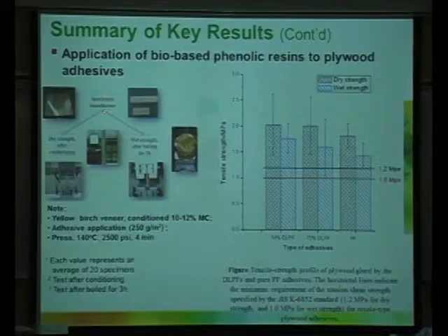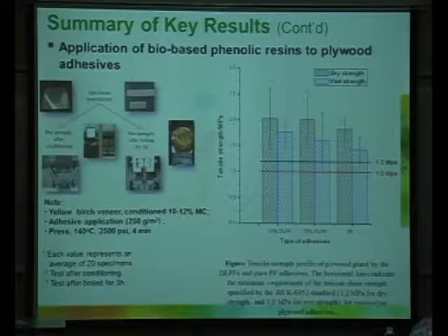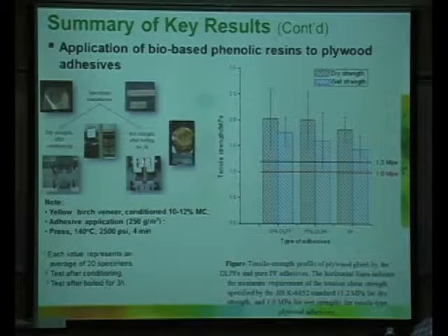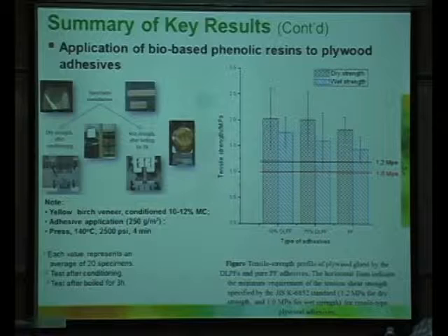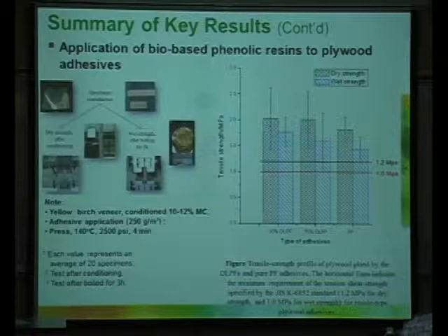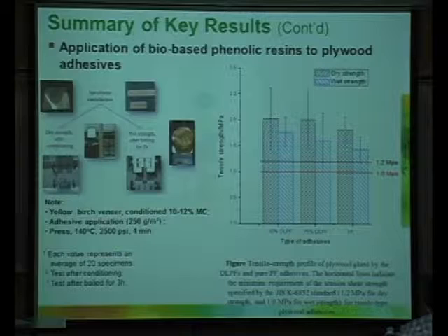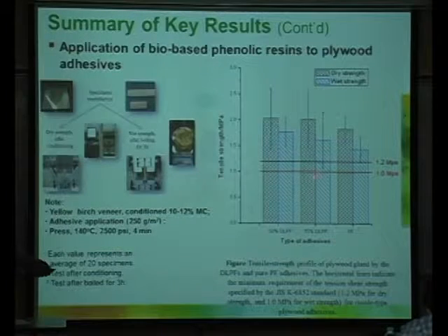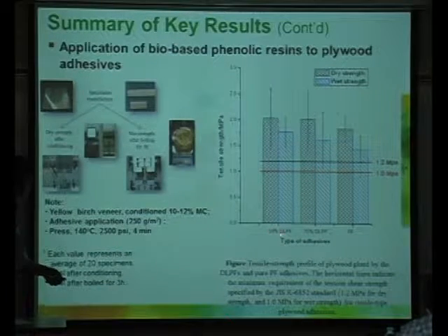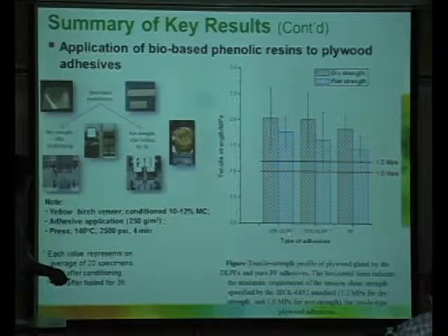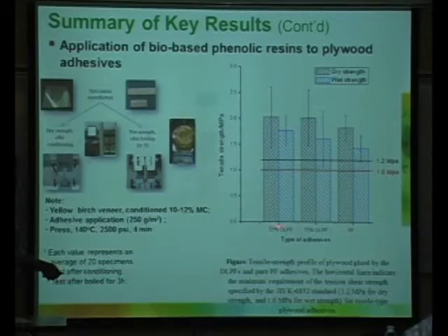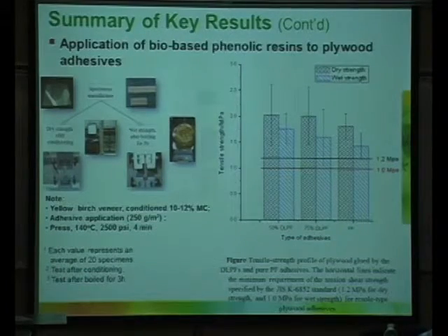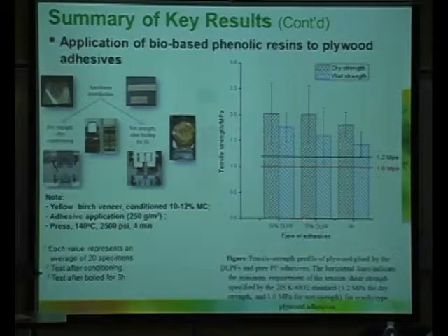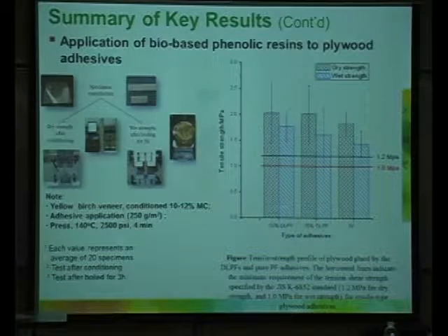We can produce some resin, and then use it as an adhesive to bond plywood, and the plywood can be tested for the strength, the bond strength. And this is a comparison with PF. PF is a pure phenol formaldehyde resin. That's the control. That's the petroleum-based phenol formaldehyde resin. That's the commercial resin. And then this is the bio-based resin. 50% DLPF means depolymerized lignin-based phenol formaldehyde resin, replacing 50% of the phenol by using this bio-based phenol. And 75% DLPF is a 75% replacement.